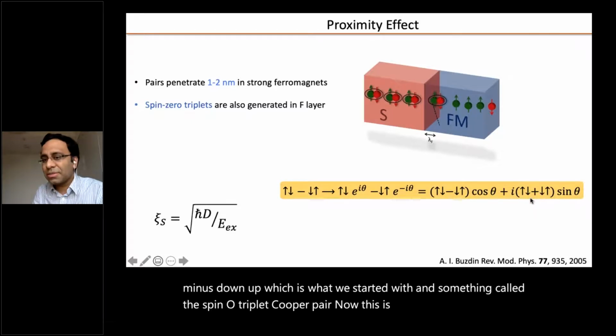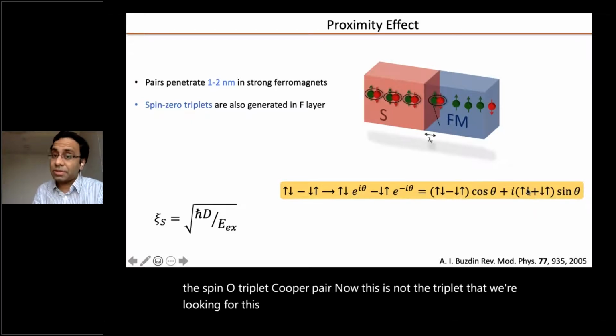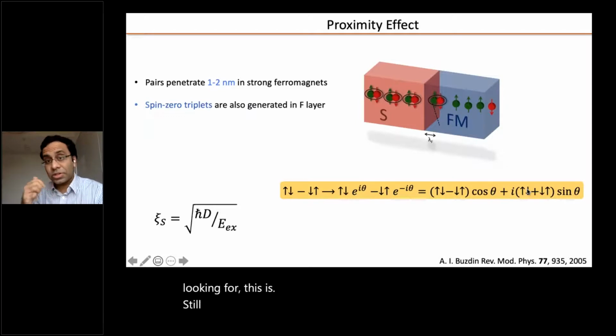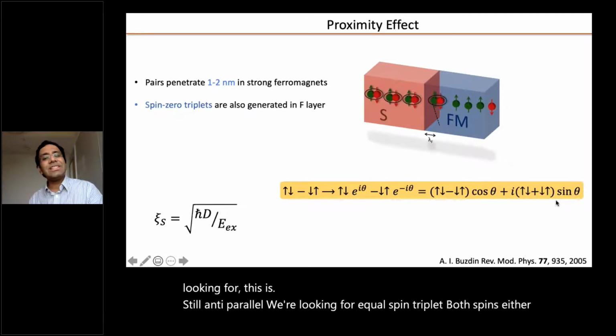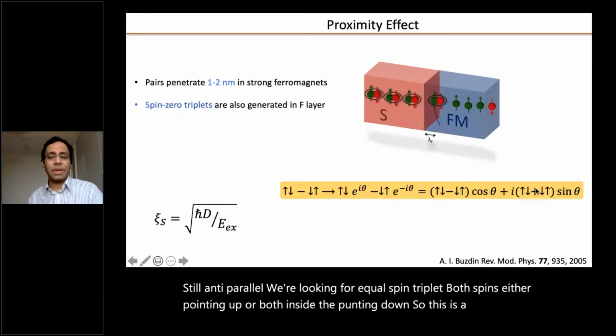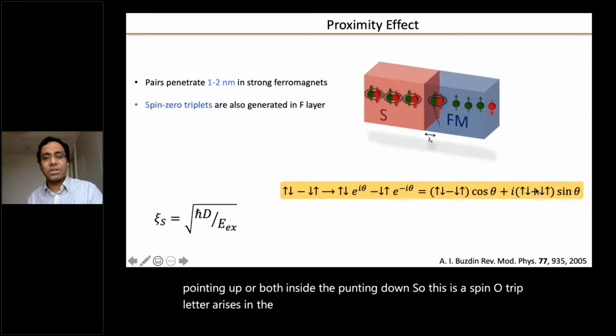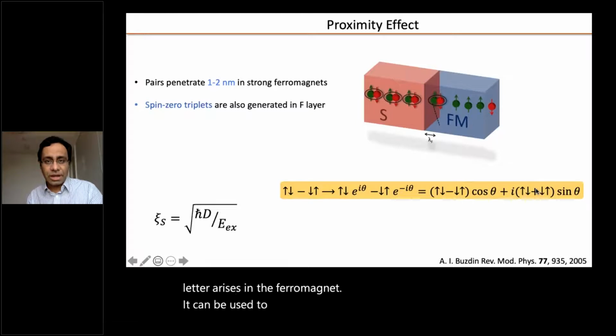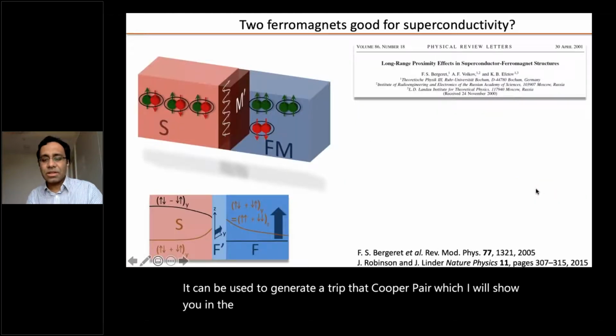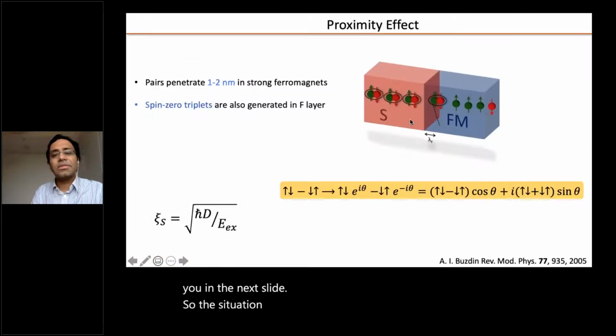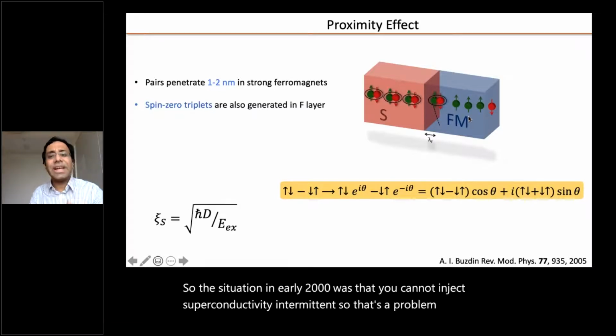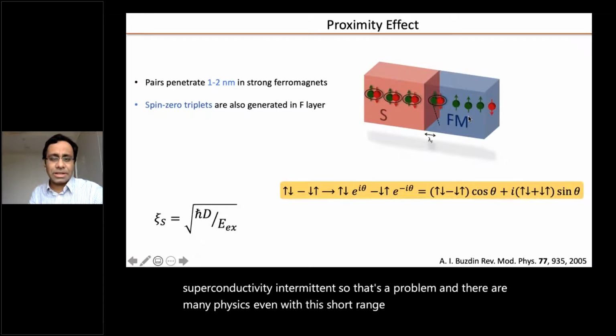This is still anti-parallel. We are looking for equal spin triplet, both spins either pointing up or both spins pointing down. So this is a spin-zero triplet that arises in the ferromagnet. It can be used to generate a triplet Cooper pair, which I will show you in the next slide. So the situation in early 2000 was that you cannot inject superconductivity into a ferromagnet. So that's a problem, and there are many physics even with this short-range interaction between a superconductor and a ferromagnet.